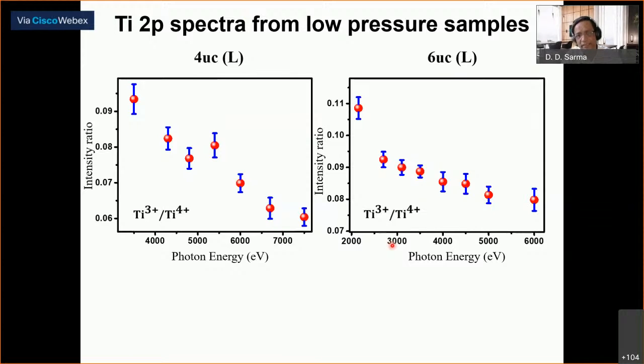Now we need to analyze this. The very fact that the intensity is going down as I increase the photon energy tells me that the titanium 3+ is, relatively speaking, towards the interface, and its intensity decreases as I go deeper into the substrate, into STO. But in order to know exactly how it is distributed, you have to model, and you take different models and calculate what is the expected variation, comparing with the experimental result to find out what kind of charge carrier distribution of this extra 3d electron of titanium would be compatible with what we observe experimentally.